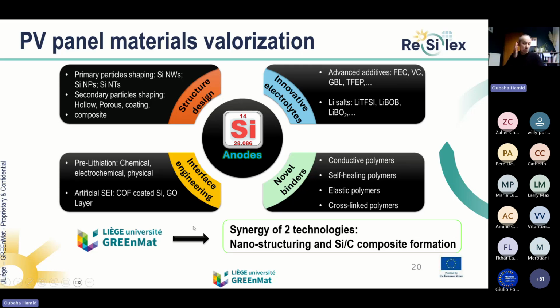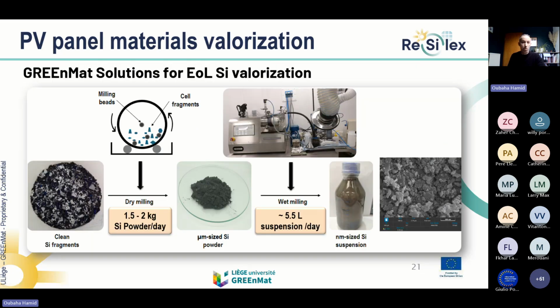In Greenmat and in the Resilex project, we decided at Greenmat to opt for a synergy between two technologies: nanostructuring of the silicon and silicon carbon composite formation. To do so, we received from partners that are responsible for recovery and purification of the silicon, clean and purified silicon fragments. The process involves two steps of milling. So one dry milling, in which we can treat more than 2 kilograms per day.